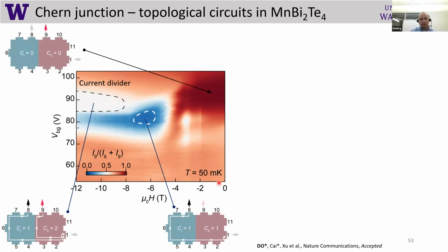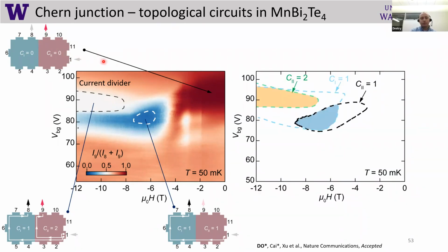And we can also switch off our topological states by just using magnetic field. So low magnetic field allows us to have just diffusive transport. In diffusive transport, it's clear that current would flow to the nearest terminal, in this case to terminal 9 instead of terminal 8. So we just have diffusive transport of electrons here. And I just wanted to show you side by side with my phase diagram of each domain, showing how this yellow region with Chern number 1 and 2 corresponds to the current divider, and this white region here corresponds to the blue region here, where we turned off our edge states.